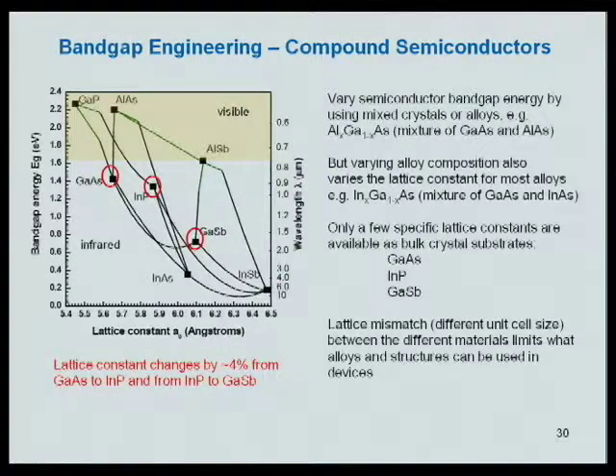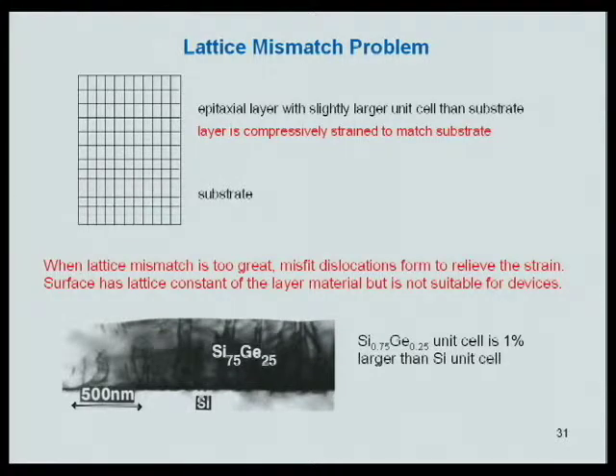And this causes problems. And you can see an example of the kind of problems it causes here, where I'm showing a 25% mixture of silicon and germanium grown on top of silicon. If the lattice mismatch between the lattice constant of the two materials is very small, what happens when you do the epitaxy is that the epitaxial layer adjusts itself so that the lattice constant in the plane matches the one of the substrate. And it adjusts itself by either expanding in the vertical direction, i.e. it's compressed, or expanding horizontally, in which case it's under tension.